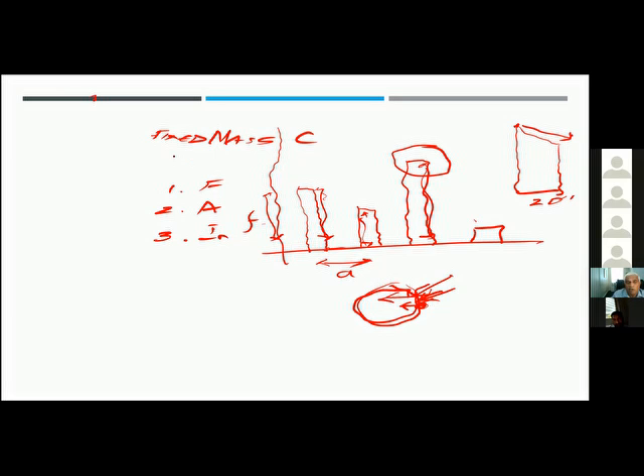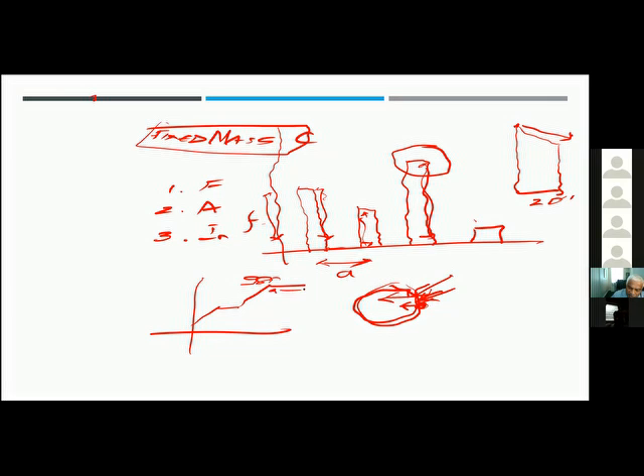And the beauty of this is at the end of the process, whatever time it is, at 980, suppose I have to draw the temperature curve. You are at 700 and you go to 980. At 980, this maintenance takes place, and this whole process happens here. Once this is over, you stabilize and then you take it for quenching. So in the conventional system, this part is where the carburizing takes place and this is where the diffusion takes place. But here you can do it together because carburizing and diffusion are taking place almost in equilibrium.